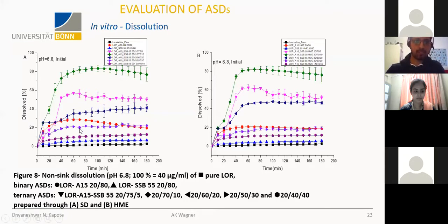loratadine in the ratio 20-75-5, we observed 20% release, which was comparable with Affinisol as a binary mixture 20-80. While in case of loratadine, when we tried Affinisol and shellac and increased the Affinisol concentration to 60%, we observed 40% dissolved at pH 6.8. When we decrease the ratio of shellac and increase the concentration of Affinisol, a higher amount of API was released, which was attributed to increased intermolecular interaction.